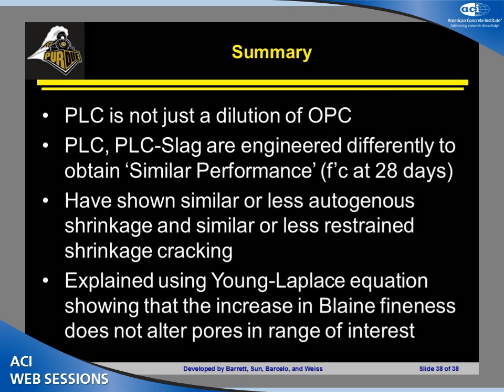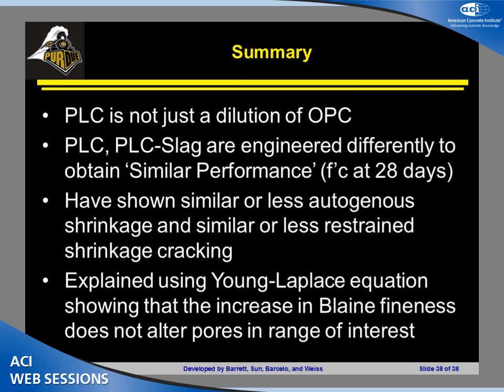So again, the summary of the overall observations that we can make here: PLC is really not just the dilution of the OPC. It's not really taking 15% of the clinker away and hoping for the best. It's really a system that's engineered to have finer particle sizes to increase the reactivity of those systems and give you a very similar pore size distribution. And because of this, we tend to see a lot of similar properties: similar strength, similar modulus, similar transport properties, similar shrinkage. It's not surprising because we've got a very similar pore size distribution in those that's really been engineered. The PLC and the PLC slag systems are engineered differently to obtain similar performance. Again, more fine grinding to get that similar performance.